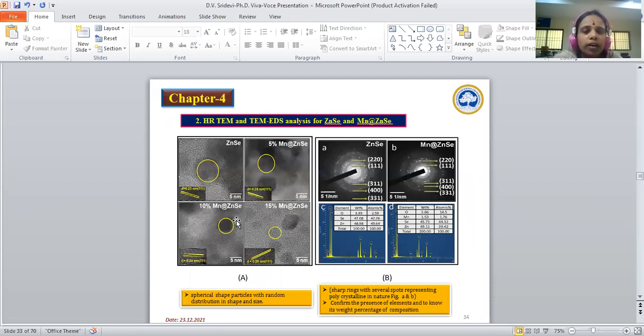This slide shows HR-TEM and TEM-EDAX analysis for zinc selenide and manganese doped zinc selenide nanoparticles. Figure A shows all the samples are spherical in shape and the particles were randomly distributed. Figure B, small a and b, shows the selected area electron diffraction pattern with sharp rings and several spots, representing that all the synthesized nanoparticles are polycrystalline in nature. This data is in good agreement with the powder XRD. Figure C and D show TEM-EDAX analysis of the synthesized compound, which confirms the presence of zinc, selenium and manganese and gives the weight percentage of its composition.